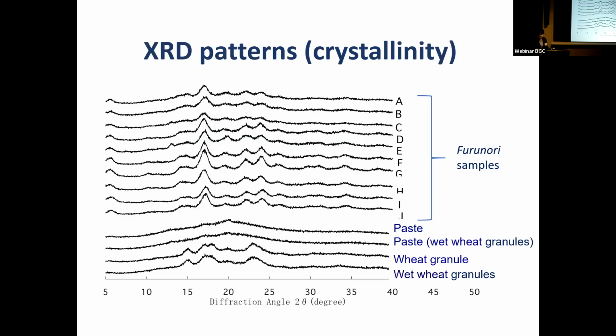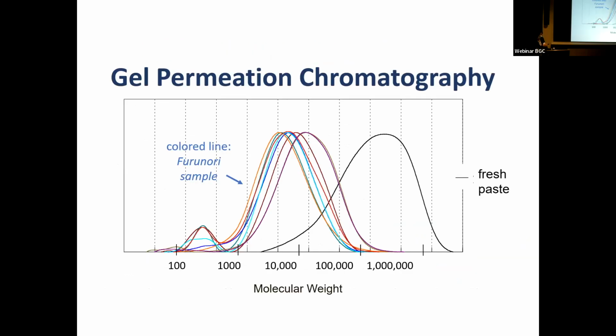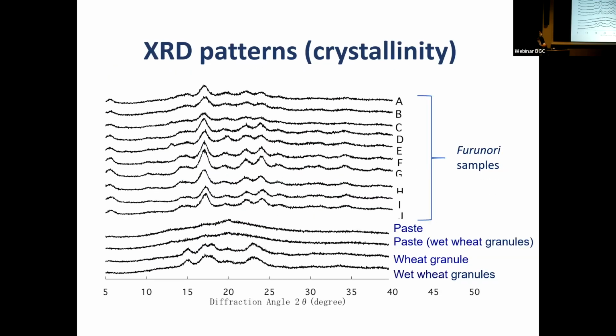The XRD results of all of the furunori samples that were tested revealed a recrystallized pattern. This suggests that some furunori characteristics stem from the retrogradation caused by storage in a cool place for about a decade. On the other hand,